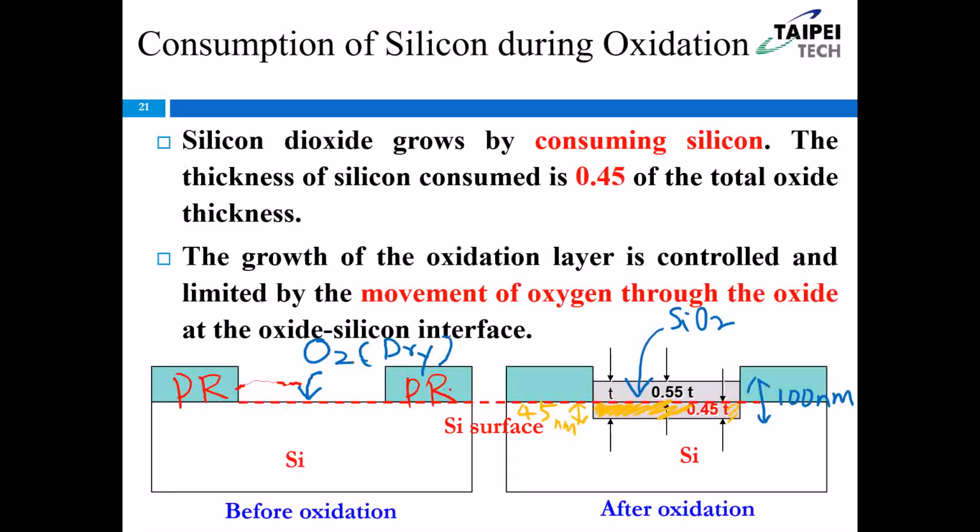And then I put this silicon wafer into the furnace, okay? The oxygen atoms only react with the silicon here, so that's the reason only the central region has the silicon dioxide. We call it local oxidation, 局部的氧化, and it only happens here because only the central region has the silicon surface, right? So the local oxidation only happens in the central region, okay?